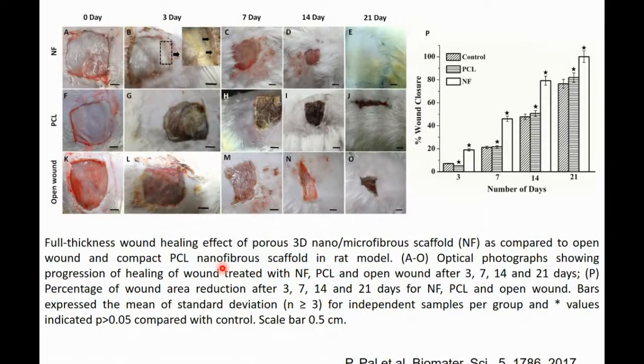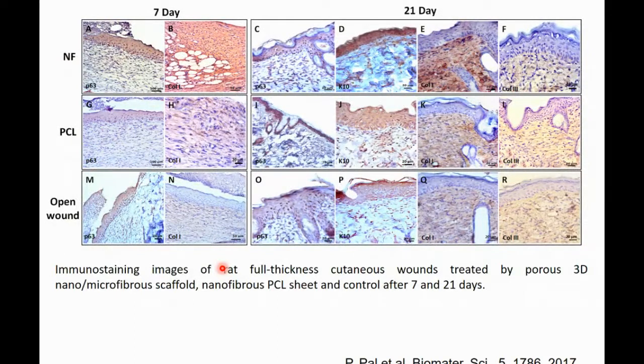And this kind of skin graft we have tested with animals, and we have seen that in 21 days' time there is a complete healing of the wounds. Therefore, this kind of matrix can be utilized for wound healing purposes. And while we have done the immunohistological studies, we have seen that we can have a significant reduction in scar utilizing the collagen. And usually this collagen we are using is fish scale derived collagen.